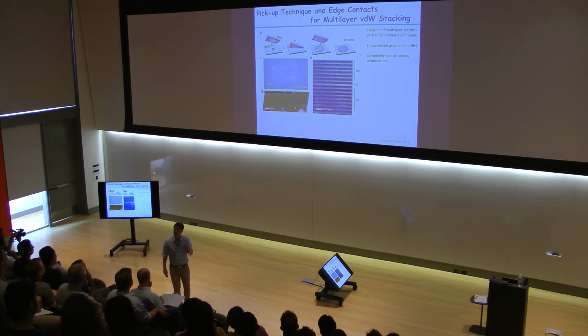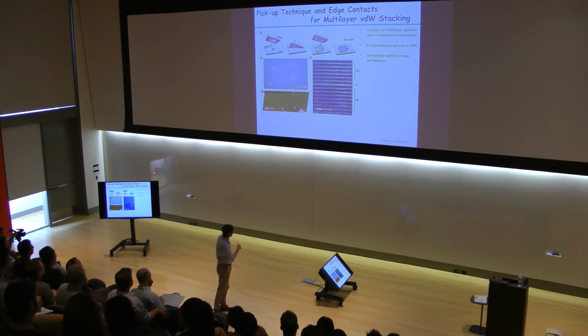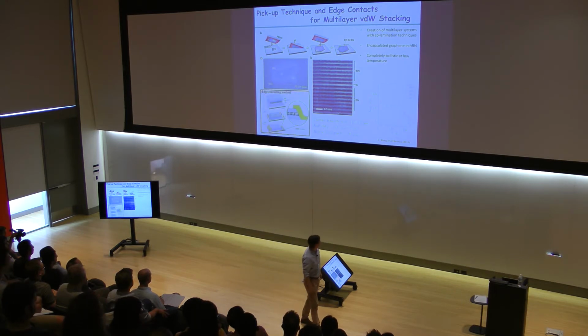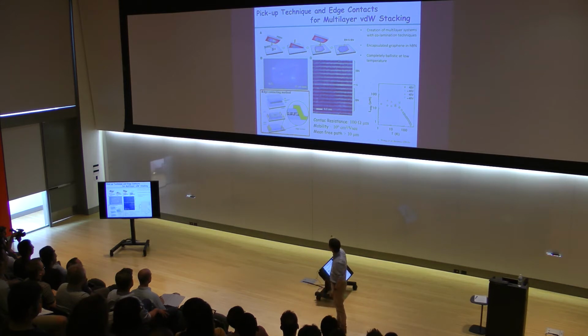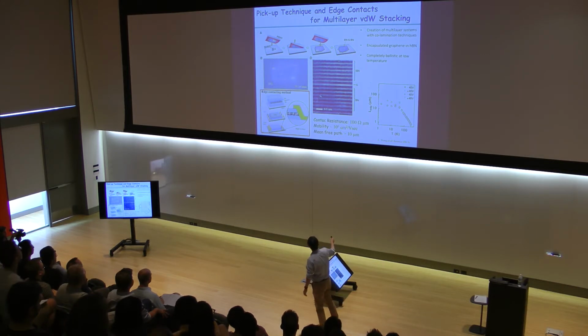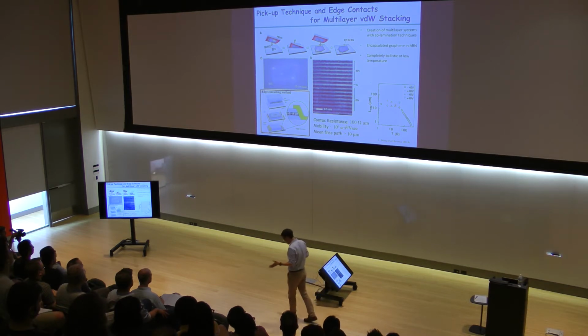MBE type of clean interface, in principle, you can also cut the stacks in a very careful manner and expose the certain atomic layer that you want to make the contact. And there has been some method developed that you can selectively contact the layers that you want. In this particular case, graphene is contacted with this gold and makes an extremely good contact, such that you can make this device based on these quantum structures where individual atomic layers can be contacted, right? So that's a very important part.